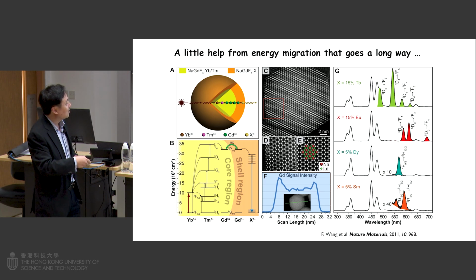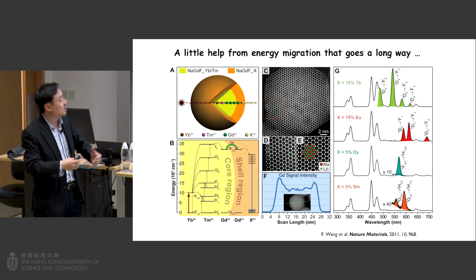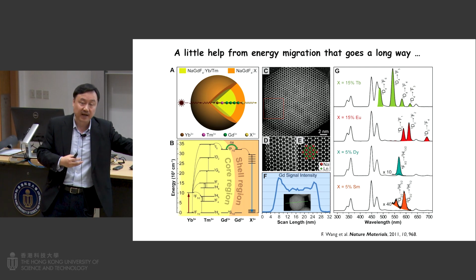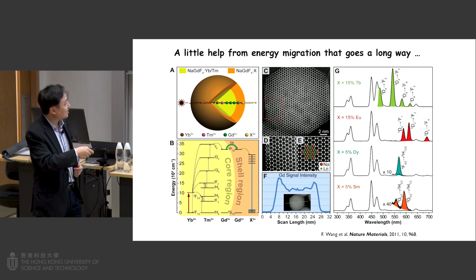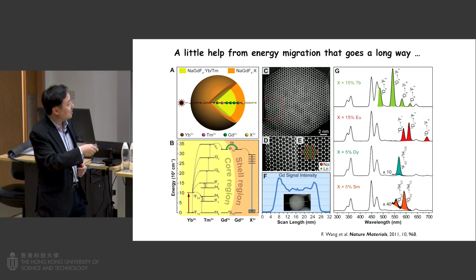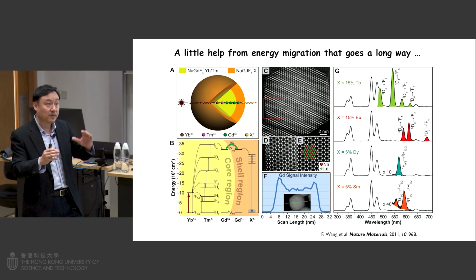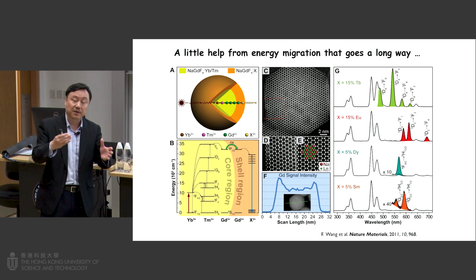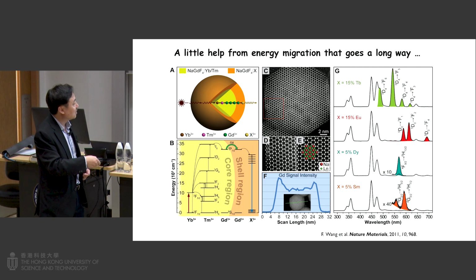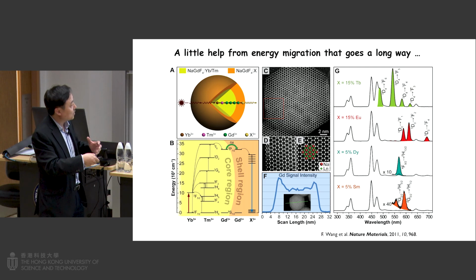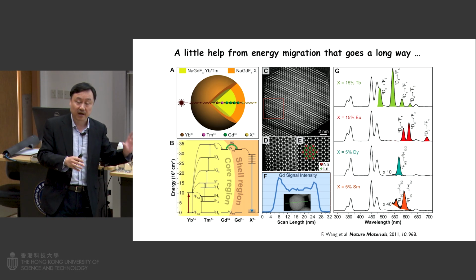You can see the scheme here. It takes the excitation energy absorbed by Yb and then transfers to Tm, then through the Gd lattice. So the Gd is within the core-shell structure, and then transfers to the emitter here. Why can Gd absorb the excitation energy and pass it to another Gd through the sublattice? If you look at the energy levels here, they don't have many intermediate states like Tm and Yb. The energy gap here is about 4 electron volts. 4 electron volts is very big, so even water vibration will not interfere with the energy transfer. That's why we use Gd for energy migration. Gd is magic. I think it's a magic element.